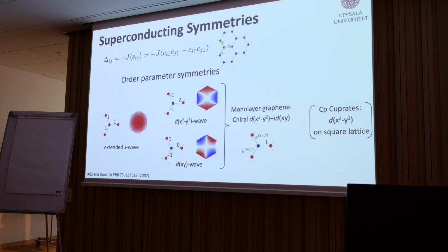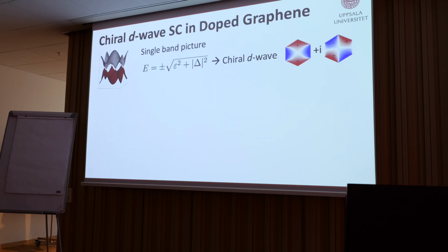And the simplest combination is to have a chiral combination, take d plus id. And in real space, that looks like nothing else than you take the three cube roots of 1 as your bond order parameters. You have the bond order parameter 1, e to the 2 pi over 3, and e to the 4 pi over 3 here. And that is the solution that we get on the monolayer graphene if you do the same thing. And it's rather simple to understand why you get the chiral d-wave.